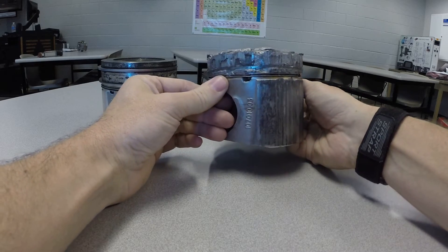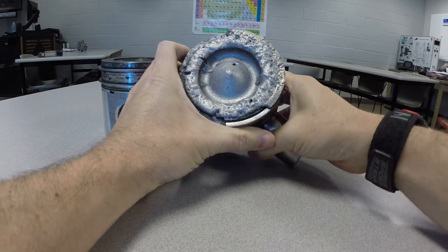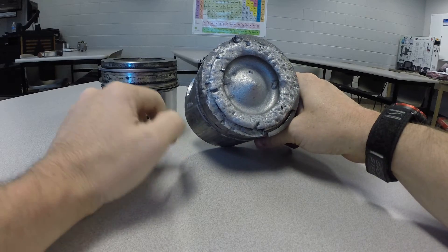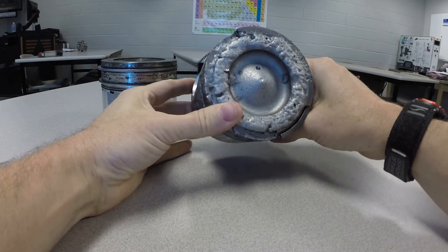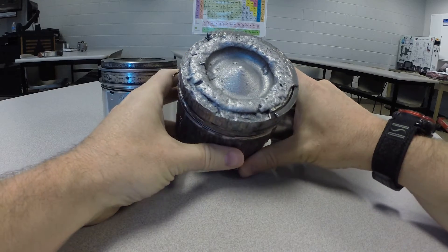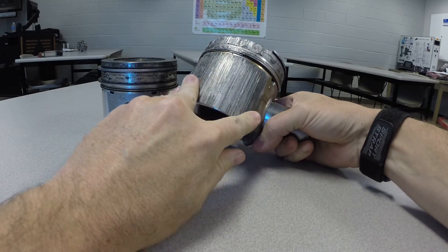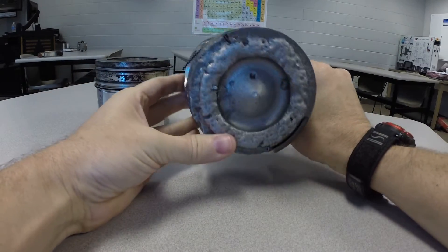We burned down through the first ring land. You can see that what's left of the upper compression ring is barely hanging in there. There's actually a chunk of the compression ring stuck there — you can see the keystone shape of that piston ring completely embedded in what was molten aluminum on the top of this piston. As the piston deformed, all the molten material streamed down the cylinder walls as the piston moved up and down, embedding aluminum on the sides and just completely ripping it into shreds. It doesn't look nice like this other one does — completely ruined.